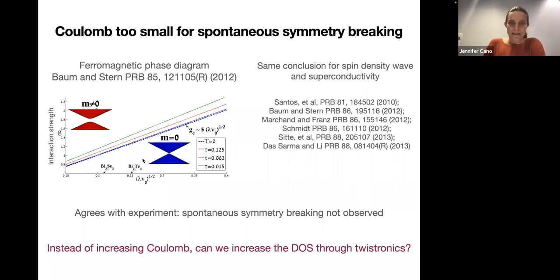And so on this plot, they marked bismuth selenide and bismuth telluride, and note that the plot doesn't go down to zero. Zero would be around here. So these two materials, which are the two most well-known TIs, are pretty close to the critical interaction strength, but not high enough. And so we wouldn't expect spontaneous symmetry breaking in these materials according to this simple calculation, because the Coulomb interaction is not strong enough. And this agrees with the experiment that we don't observe spontaneous ferromagnetism on the surface of a TI. So how could we reach this?